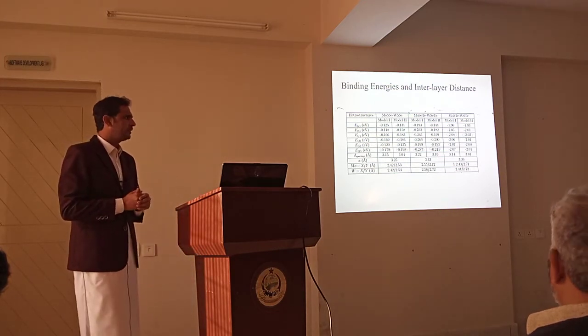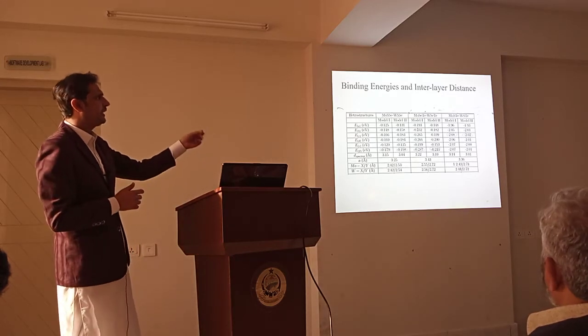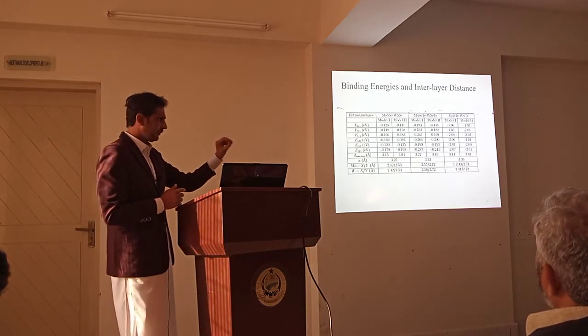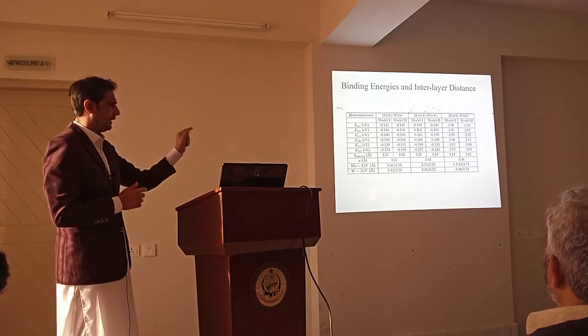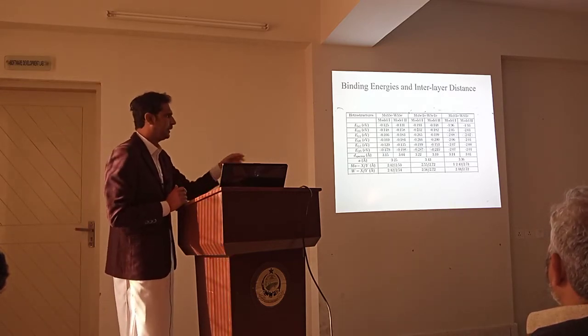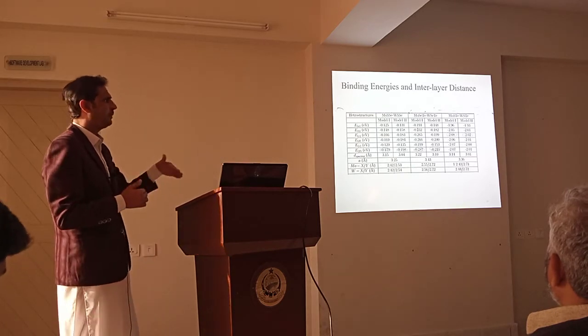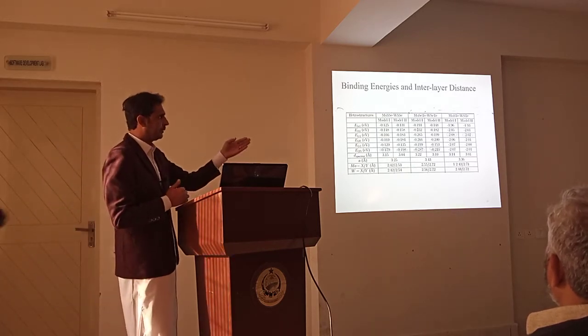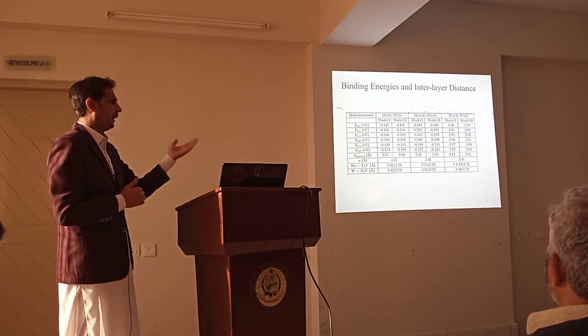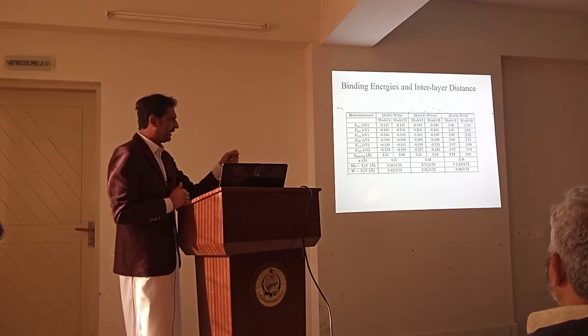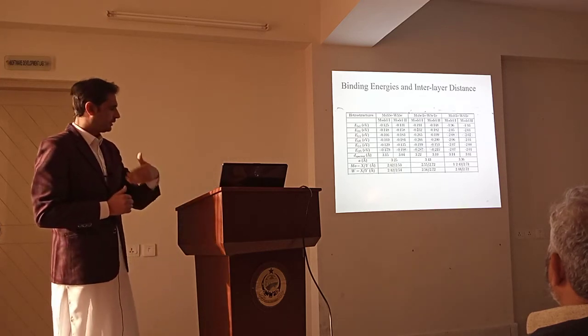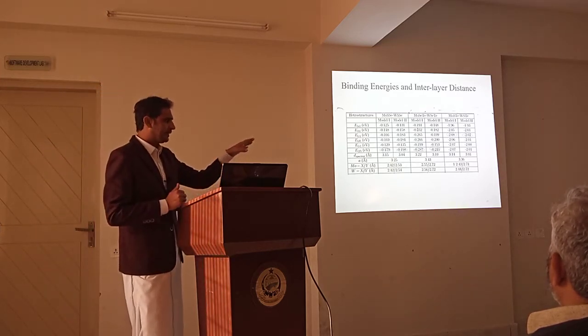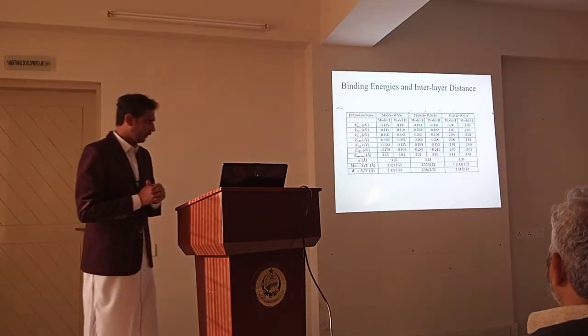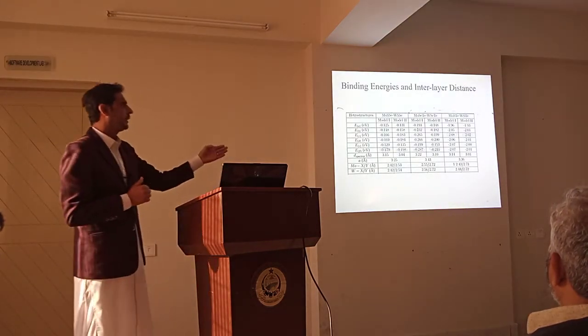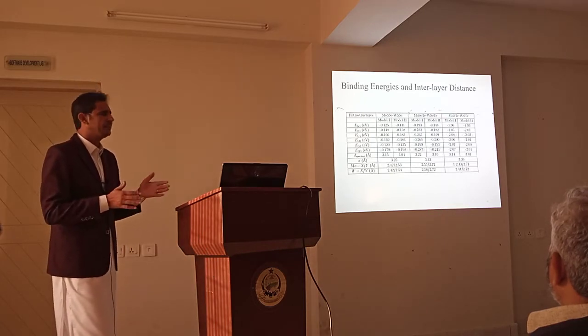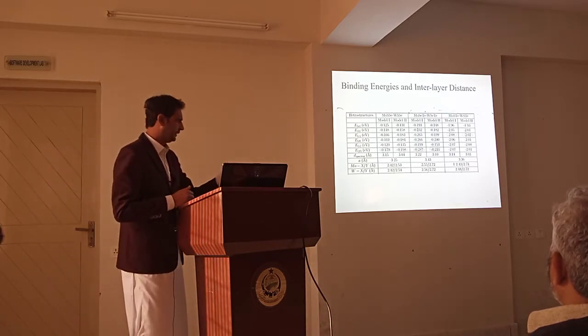Here are the calculated binding energy and interlayer distance. If we look at the MoSSe, WSSe van der Waals structures for model 1 and model 2, the F stacking is the more favorable stacking because its binding energy is lower as compared to the other stackings. Similarly, for MoSeTe, WSeTe, also the F stacking, while in the case of MoSTe, WSTe, the E stacking is more stable because its binding energy is more negative as compared to the others. Here I also represent the d spacing, meaning interlayer distance, of these more favorable stackings.